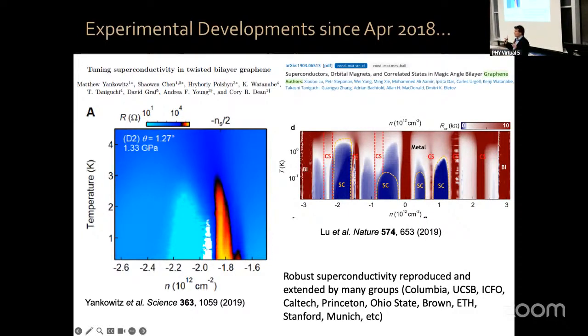But then they did something very clever: they applied hydrostatic pressure to the two sheets. When you apply pressure, the graphene sheets get closer, so the interlayer tunneling increases, and the magic angle condition changes. It's no longer at 1.1 degrees, but shifts to a higher angle.